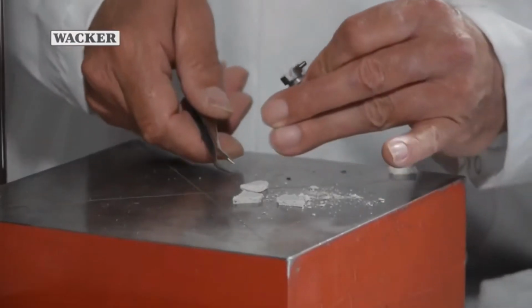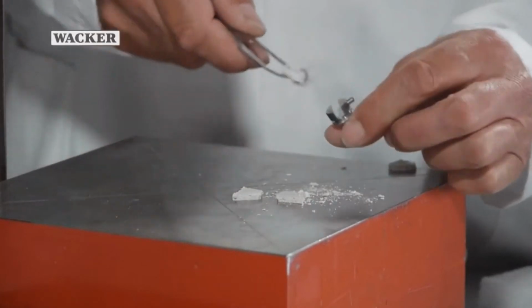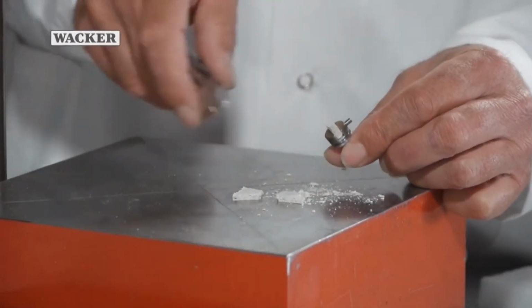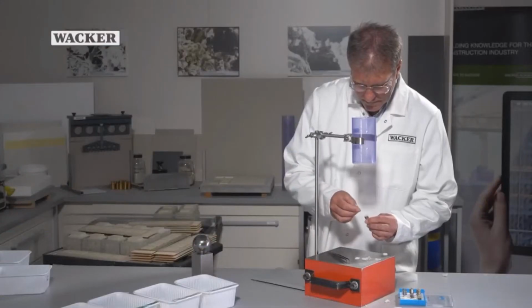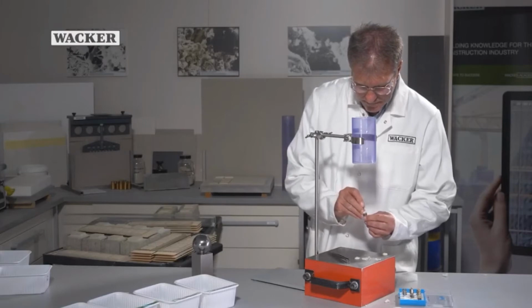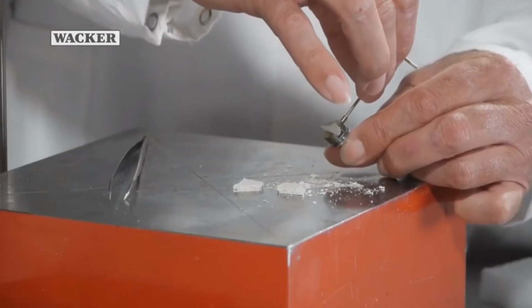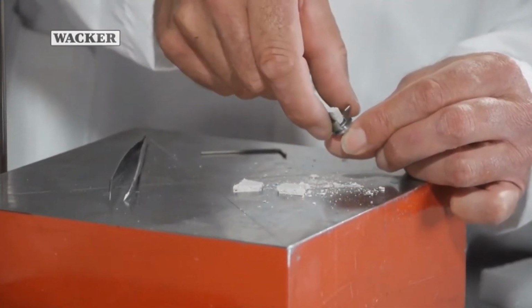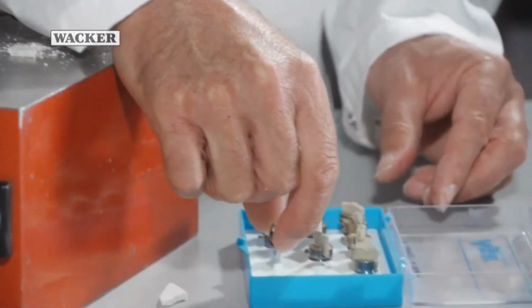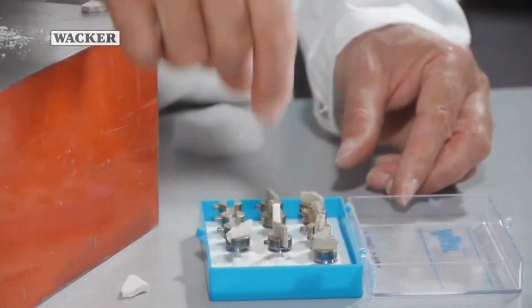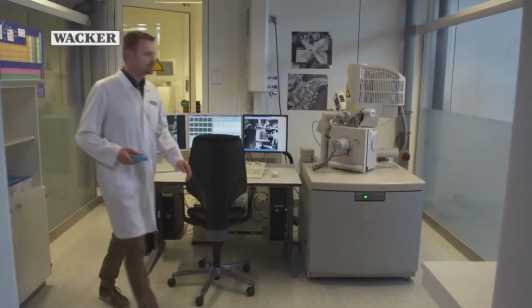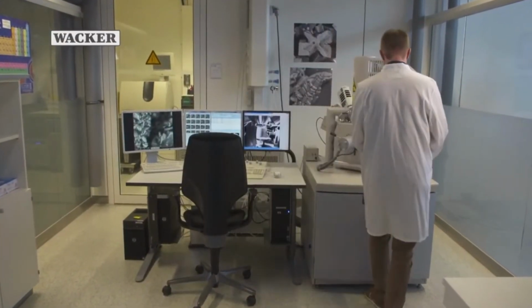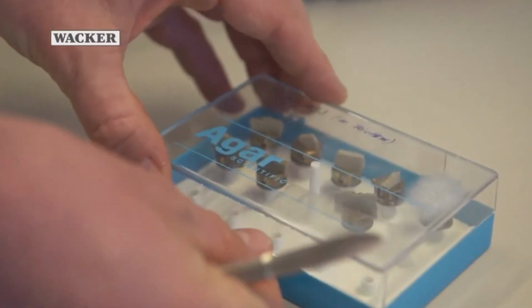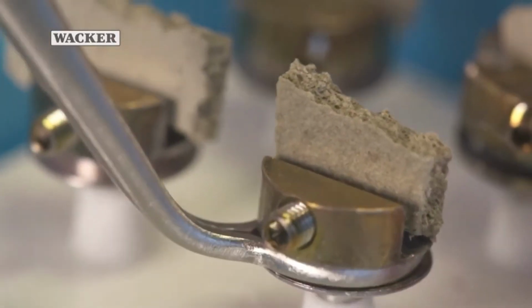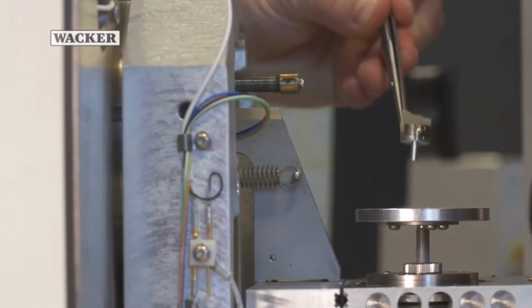Next, we will use a scanning electron microscope to study the effects that the polymer has on the tile adhesive. This is done by examining samples of unmodified tile adhesive and adhesive modified with 12% VINNAPAS dispersible polymer powder, observing each one both before and after the impact impulse. The high-powered microscope allows us to see the cement crystals that have formed, as well as the polymer bridges within the test specimen.